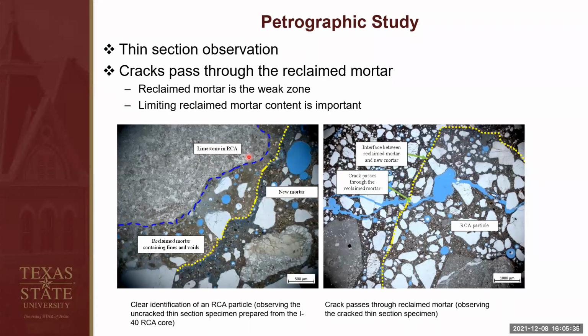We also did a thin section observation using microscope, and we can clearly see the reclaimed mortar here. As you can see, the color is gray. And we also see the cracks propagate through the reclaimed mortar. So that's why we concluded that the reclaimed mortar is a weak zone. So if we want to control RCA concrete properties, we want to limit reclaimed mortar content in the RCA sample. It is very similar to what we want to do for our RAP concrete. We want to control the asphalt content. Here we want to control the reclaimed mortar content.